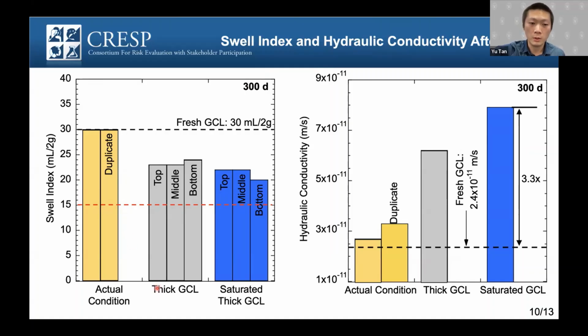And we took a close look at the thicker GCL. We sliced the thicker GCL into 3 layers: top, middle, and bottom. The bottom is in direct contact with the concrete. And we didn't find significant differences between the top layer, middle layer, and bottom layer in the saturated condition and also in the thick condition. It means that the reaction reaches equilibrium in the cross section of the thicker GCL.